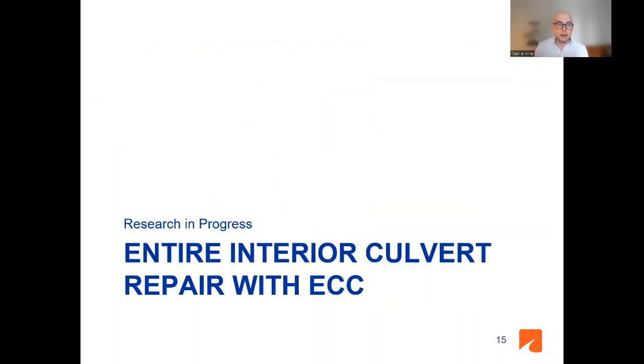Now, next, I want to talk about research in progress, and this is particular to the repair of the entire interior culvert with ECC. First, I want to mention what the challenges are, because this is actually quite difficult. When you do the repair of the invert, gravity in a way is your friend to hold the system in place, right? But when you want to do the entire culvert, especially when you are spraying into the top of the culvert, gravity will try to pull this material down, and it's difficult to generate this thickness buildup.